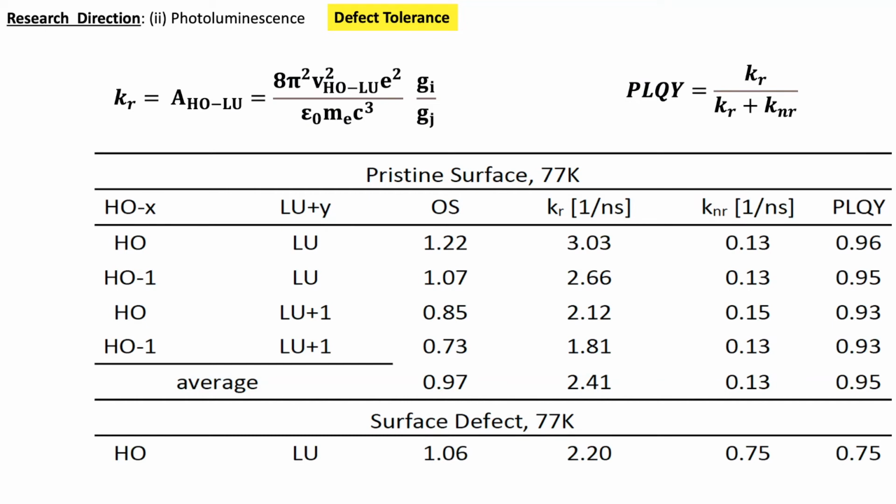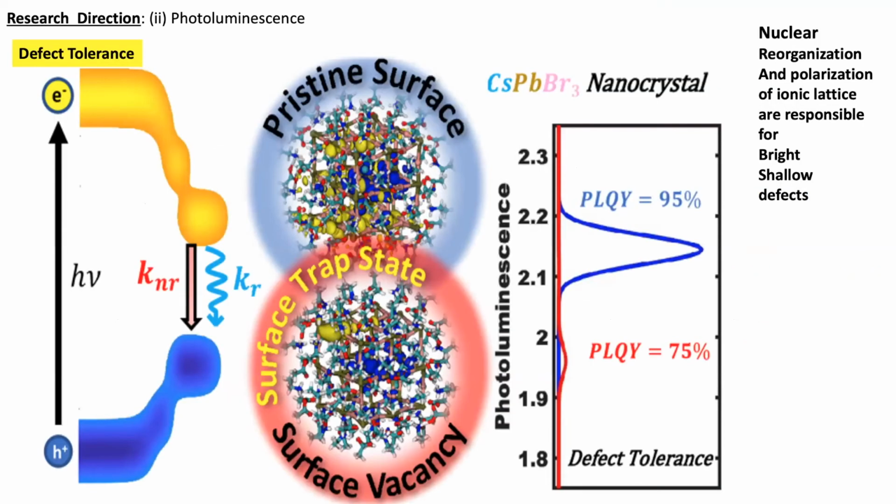For pristine it is 95%, and for defects 75%, which I wouldn't defend as the literal value or absolute truth, but the fact that they are quite close and the defect is quite bright is interesting, and probably related to the fact that defects in perovskites are compensated by polarization, and properties of materials are not deteriorated even if defects are available.